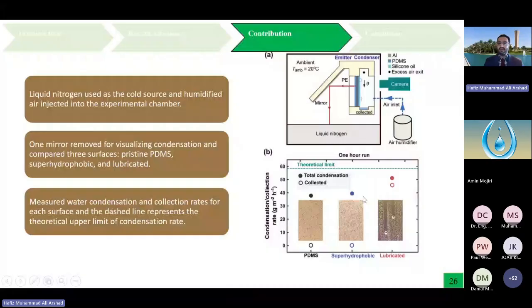But once we have lubricated oil, there was total condensation and the collection rate was almost near to the total condensation on the surface. So you can see here that we reached up to almost 50 gram per meter square per hour.